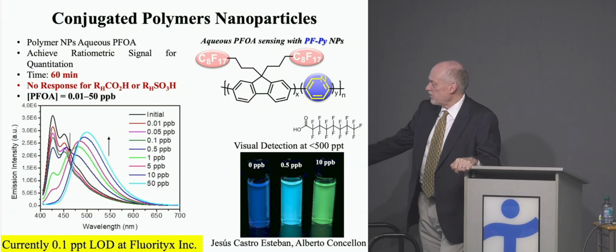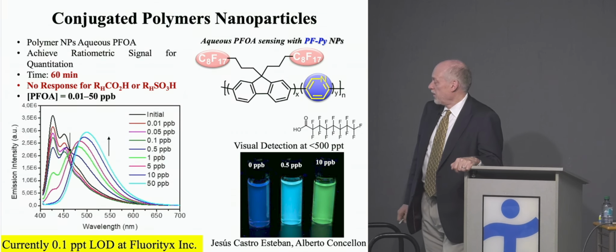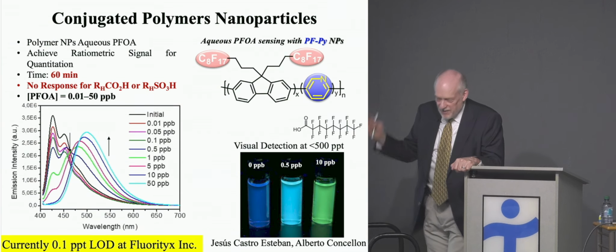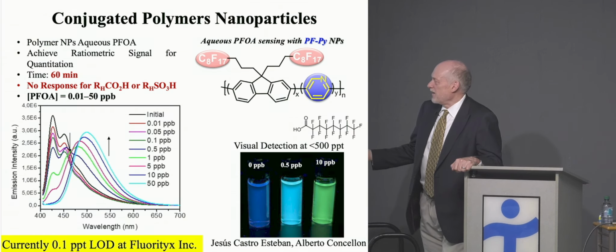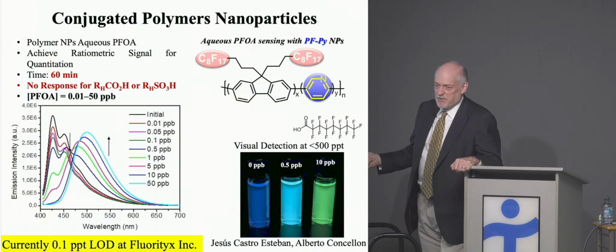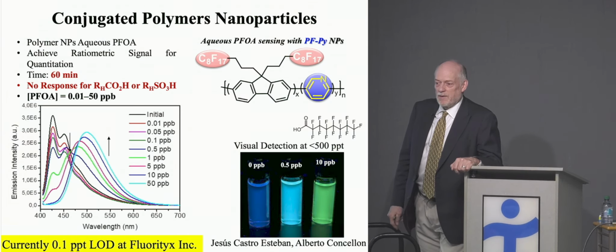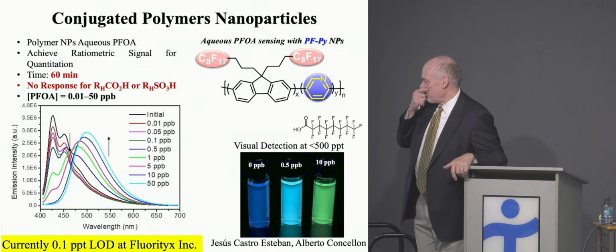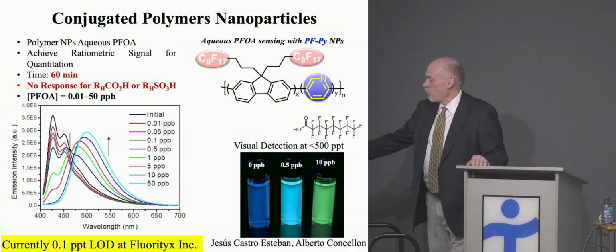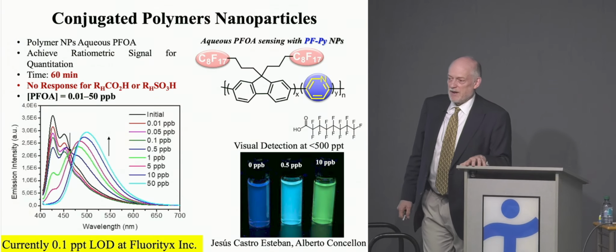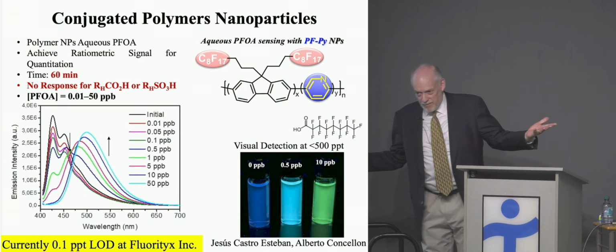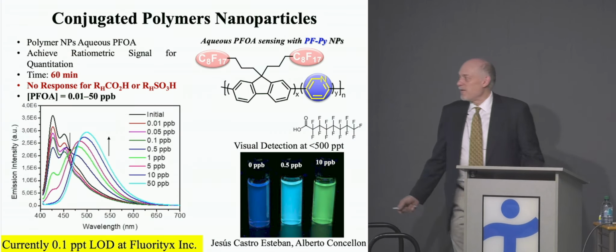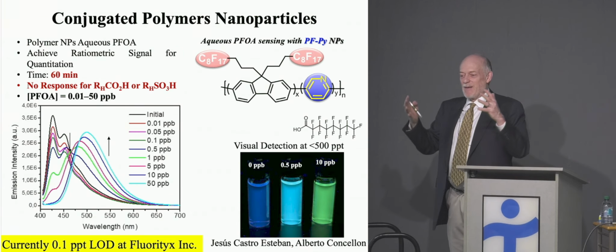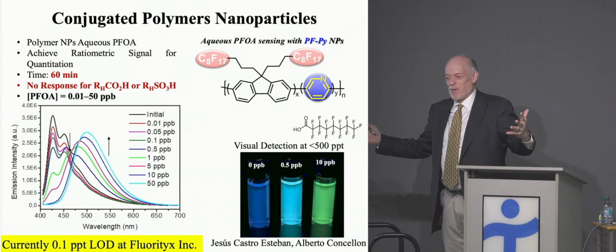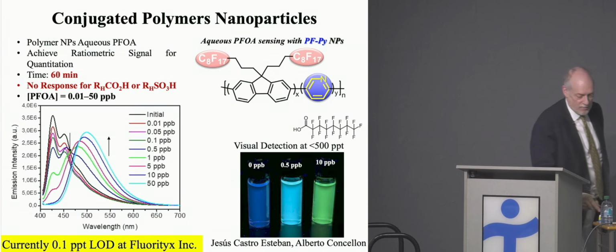And we've now transitioned this to a startup called Fluorityx. And because they sit there and iterate, in my group we were down at about 10 parts per trillion. They're down 100 times lower than us right now, with the different prototypes and devices they've made, and that is well below the EPA limit. So this is getting to where it's hard to find things that don't have 0.1. And I can tell you that the biggest challenge in this company is to try and keep things clean so we can know when our baselines are right.